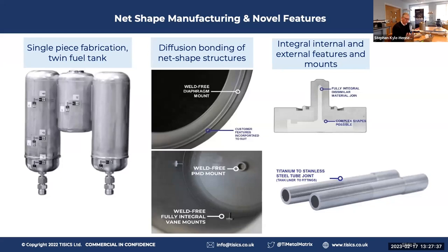This is important because the pipe work out of these tanks needs to go into pipe work in the rest of the aircraft structure. And what we can really do, which is pretty unique, is make very thin wall structures in one go. So this tank here is about 0.4 millimeter wall thickness. It'll need to be thicker for structural loads, not pressure loads, for a liquid hydrogen tank.